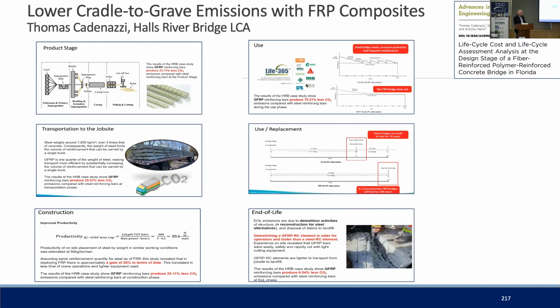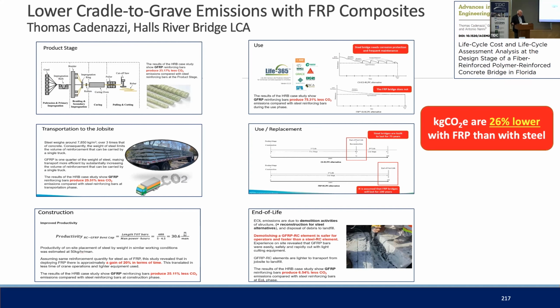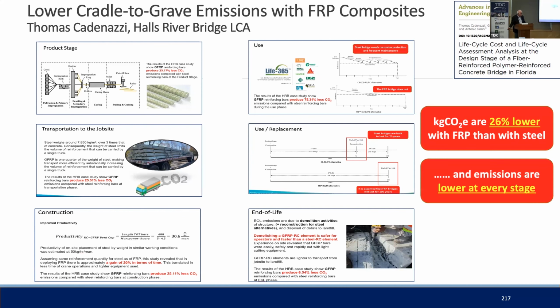Now, if Thomas Cadenazzi were here and we had more time, he would show you this collage of slides. They are taken from a presentation in an ACMA webinar that Thomas and I gave earlier this year. And in these slides, he shows for each step in the process how FRP is lower than steel: product stage, transportation, construction, use, replacement, end of life. And again, the bottom line is that the kilograms of CO2 equivalents are 26% lower with FRP than with steel, and they are lower at every stage.